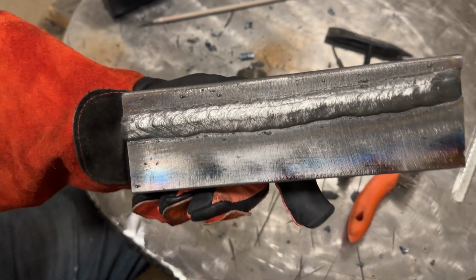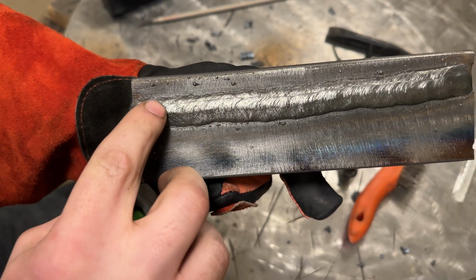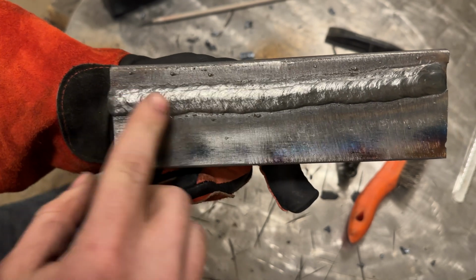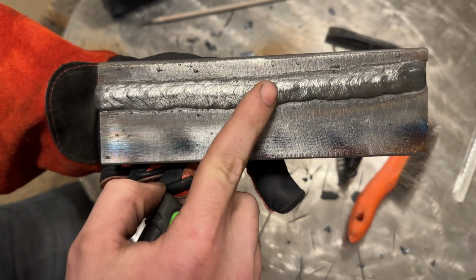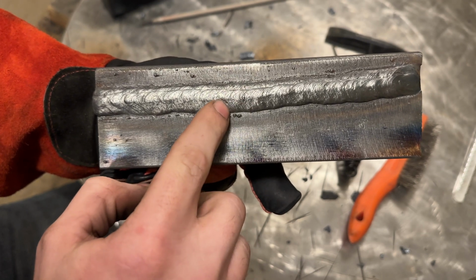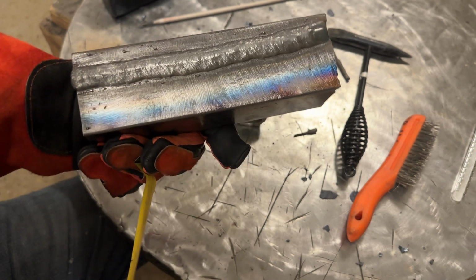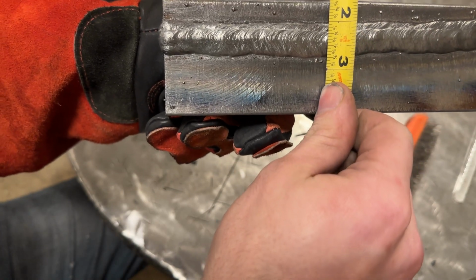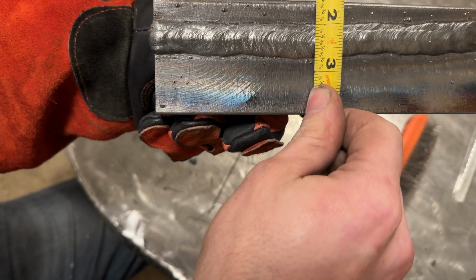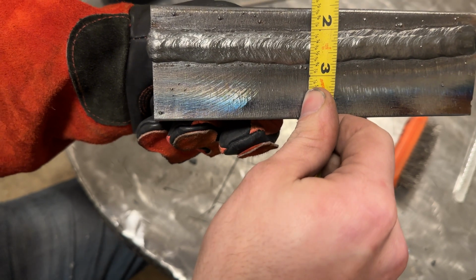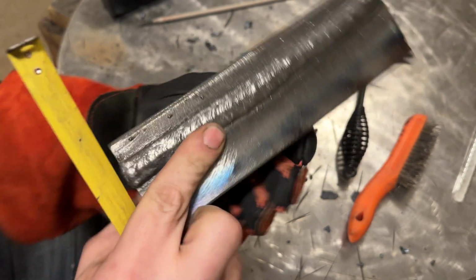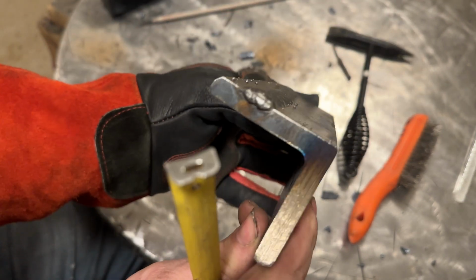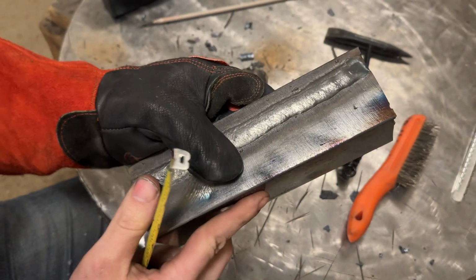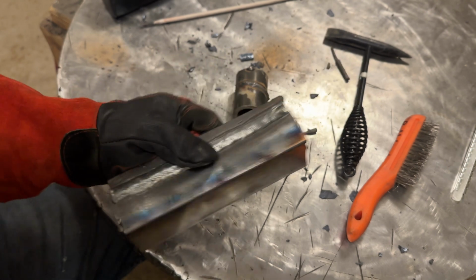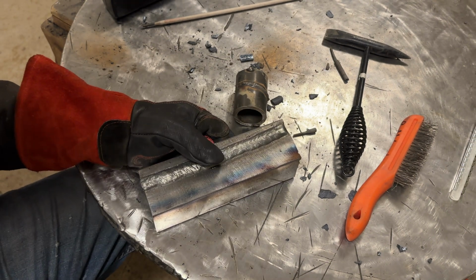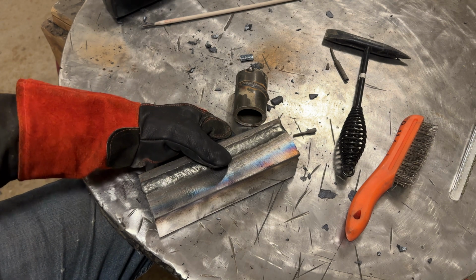All right, there you go, a 2-pass weld. You can see where this bead just hit a little bit over. When you run this right down the toe line, it has a tendency to go up over. So this is one rod that wouldn't hurt if you weld a little bit off the toe line of the first. Now, just to put it in perspective, that's a solid 5/8, almost 3/4 inch wide weld with just 2 passes. And you can see how tall that is. I mean, that is a massive amount of metal for just 2 passes. If you were using 5/32 7018s, I don't think 2 passes would even come close to that amount of metal.